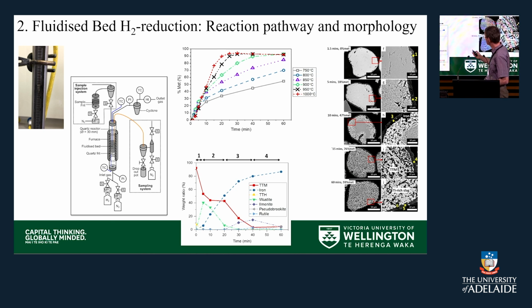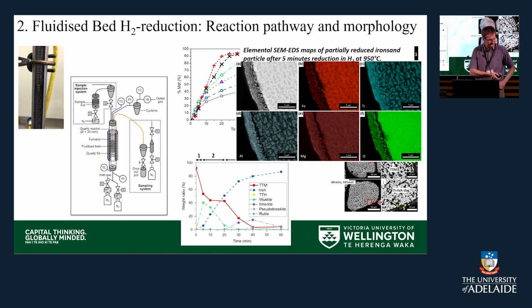If you tried to do this with a Pilbara hematite, once you got up to about 900 C, this stuff would start to stick. But we're still going at 1050, no problem, which means that we can access really rapid reactions. Building a reactor you can run at that temperature is a secondary question, but the fact that it works is really encouraging. Here's a picture just showing the titanium-rich shells on the outside of those particles.